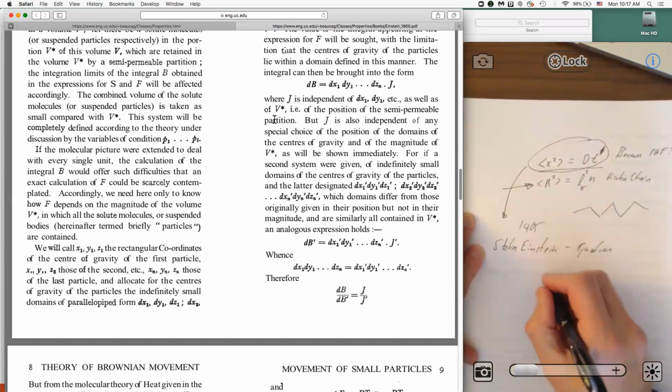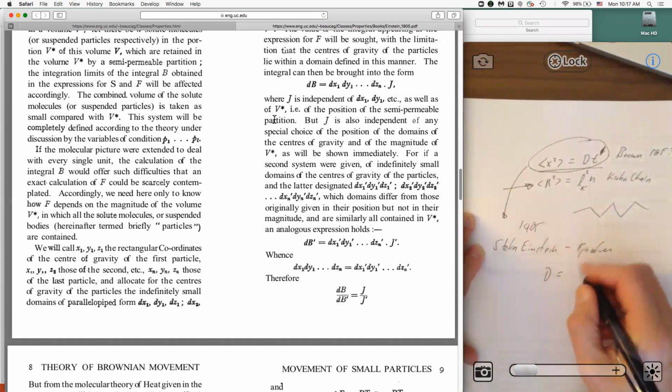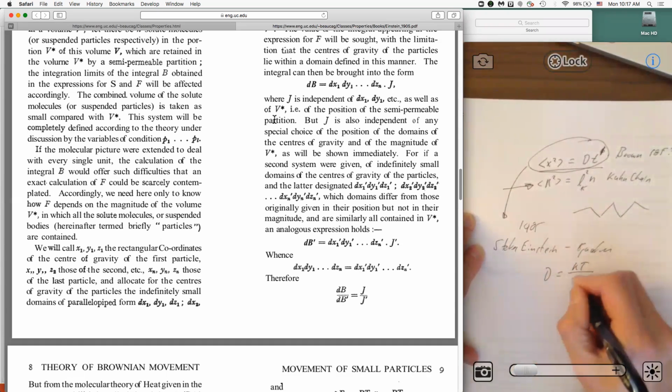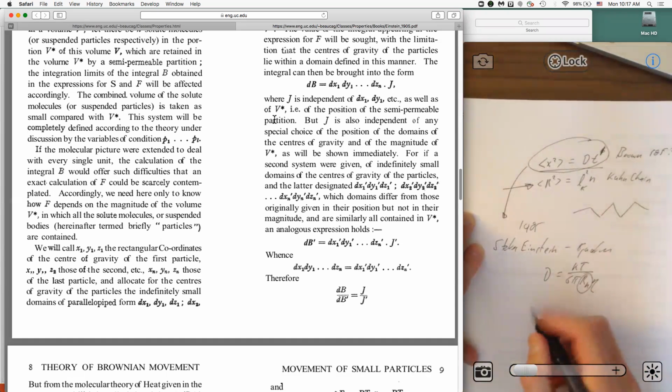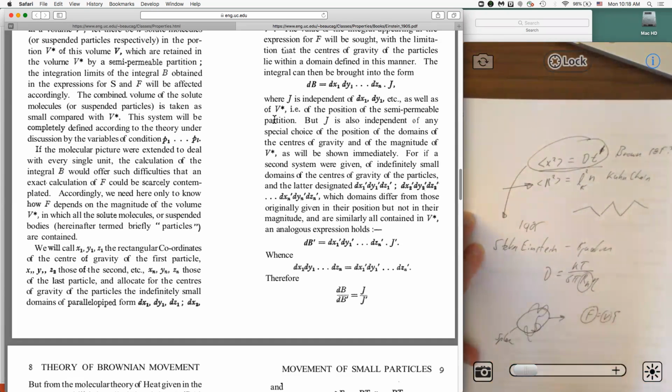The diffusion coefficient is going to be kT divided by 6 pi times the hydrodynamic radius times the viscosity. If you have an object like a polymer coil, you could say, I'm going to pull it, so I get a force, and there's a velocity and a friction coefficient associated with it. There's an equivalent sphere that would give the same force at the same velocity.